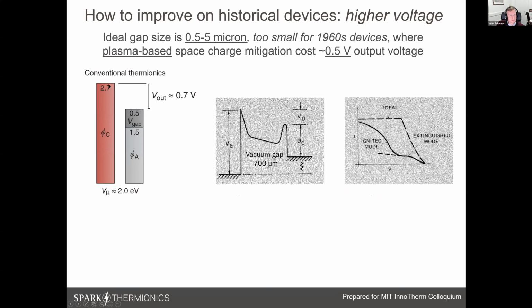This is a simplified energy diagram that's got a typical work function at 1800 Kelvin for historical thermionic devices, and typical anode and voltage in the gap for these historical plasma-based thermionic devices. So the first thing to know is that the ideal gap size for a thermionic device to mitigate space charge is on the order of a few microns. 0.5 to 5 is all pretty good, which was very difficult to achieve in the 1960s. And so instead they relied on plasma-based space charge screening, which worked incredibly well, but it did require a 0.5 volt overpotential in those days.